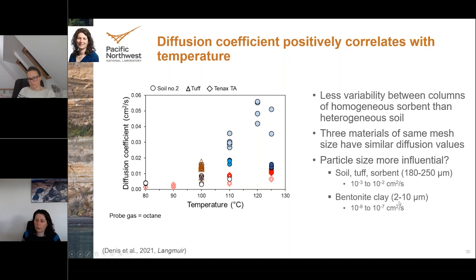So we haven't investigated this further, but it seems from these initial results that particle size might be more influential on the diffusion coefficient rather than the specific type of material that you're looking at. And then certainly with temperature, at higher temperatures you had increased diffusion, which makes sense.